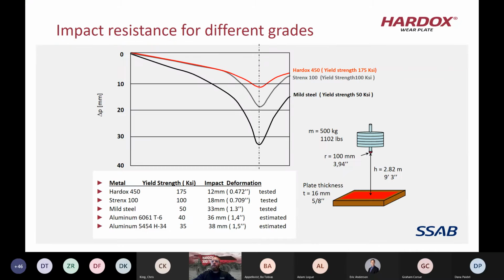So the main thing that we really see, going from a milder steel, like a 50 KSI steel, to something like a Hardox 450, is that it can take the impact and resist dents a lot better than a softer, milder steel. Basically, this chart shows that a mild 50 KSI steel would sustain a dent depth of around 30mm, as compared to a Hardox 450, which would only have a dent depth of about 10mm. This is based on the same weight being dropped on the steel from the same height and with the same radius tip.